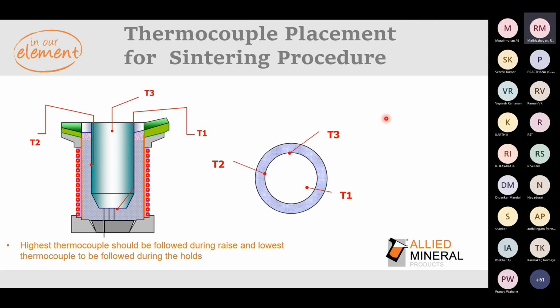So as I said before, use thermocouples during the sintering so that you can monitor the temperature. Because there's always a concern when I go to the customer's place. So what we recommend is to run at least a couple of cycles with thermocouples, note down the temperature versus kilowatt, and frame a chart. Then try to follow the kilowatt, and have a periodical check every 6 months or 1 year, whether whatever you're following is right or wrong, with the help of thermocouples.